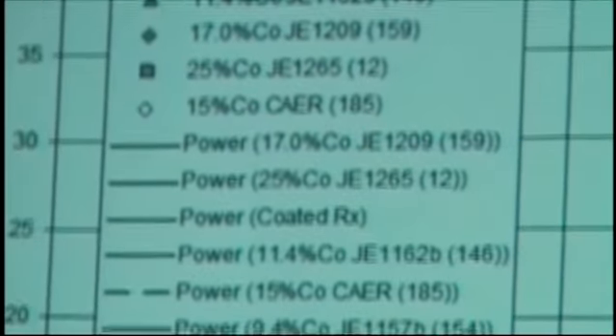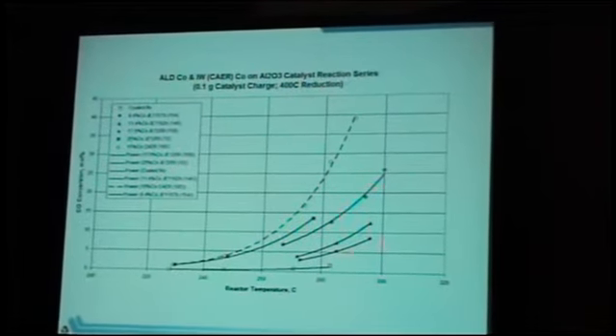In some of the comparison of materials, ALD cobalt deposition versus incipient wetness, IWI it should be. The incipient wetness was carried out at CAER labs. 0.1 grams catalyst. This is basically an introduction slide. 400 degrees C reduction, the higher temperature. And you'll notice in going down the scale, again, empty reactor, 9% cobalt, 11% cobalt, 17, 25, and the idealism of the ALD giving a better catalyst is rather well demonstrated here.